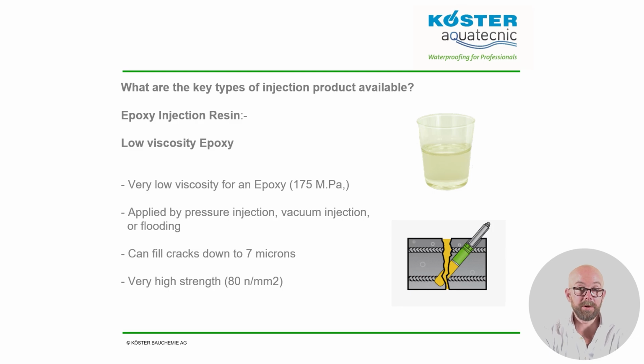The best products have a very low viscosity of 175 millipascals. This is less than half the viscosity of some of the older style epoxies used for injection and will be described as a thin liquid. The low viscosity means it can be used in even the smallest of cracks at very low injection pressure and can even be gravity fed into repaired floor cracks.